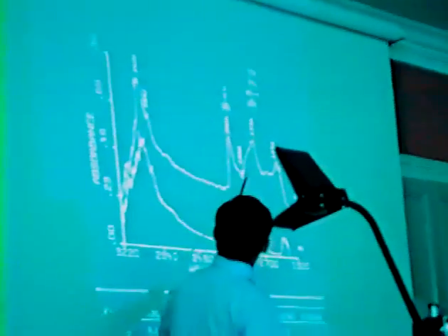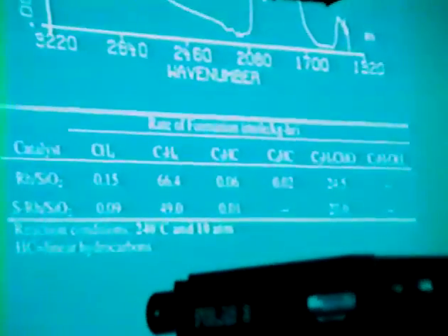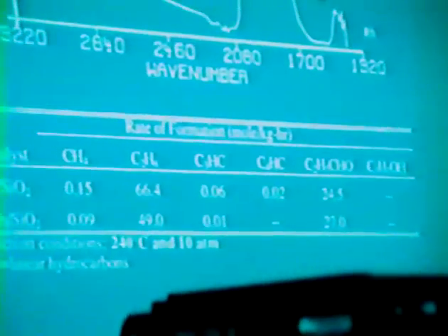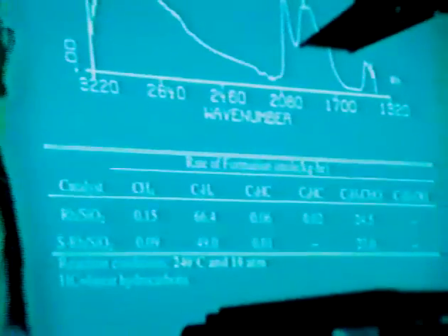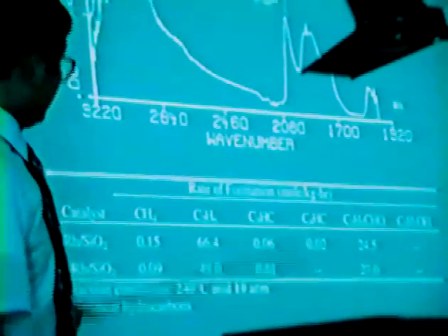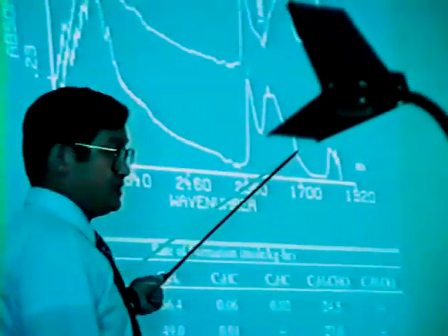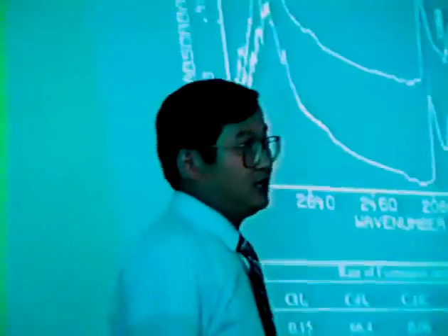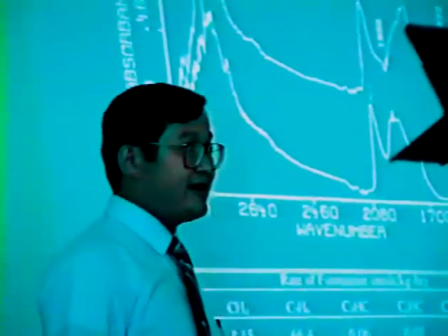Okay, this result here was conducted at high pressure, so we can clearly see there are an aldehyde band and linear and bridge CO bands, and extended carbon-hydrogen stretching bands of ethylene species and adsorbed species. One of the questions that's often raised in in-situ infrared spectroscopy studies is whether the species we observe in the infrared spectrum are merely spectators. So we have tried to combine the in-situ infrared technique with the isotopic transient technique, which was proposed by Professor Tamaru a long time ago, to study this reaction. Next please.